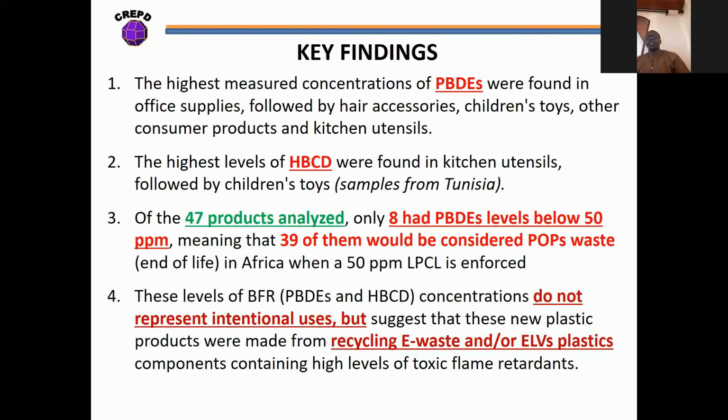We also know that of the 47 products analyzed, only 8 products had PBDE levels below 50 ppm, meaning that 39 of them will be considered POP waste at the end of life in Africa.